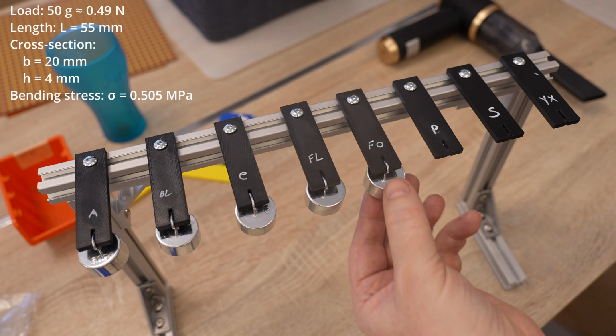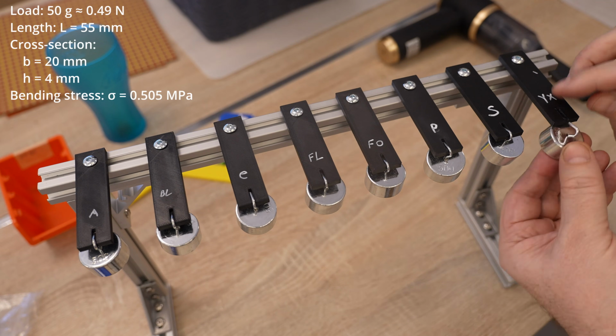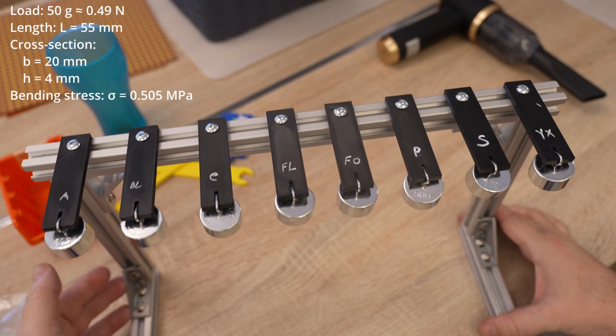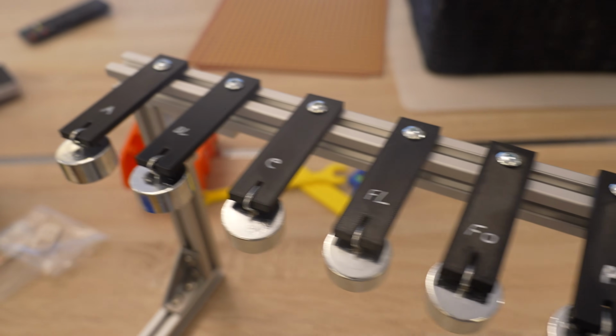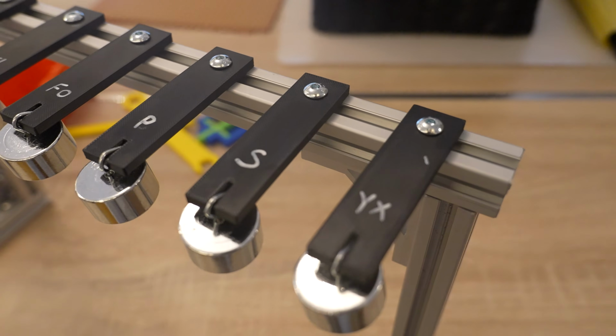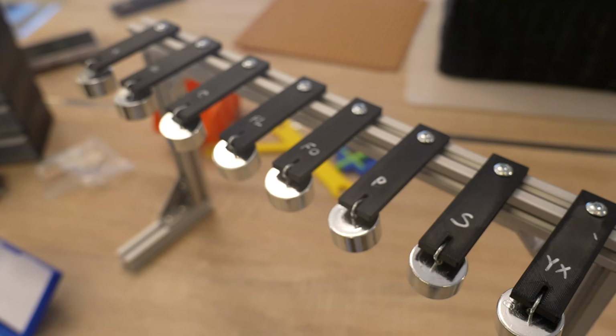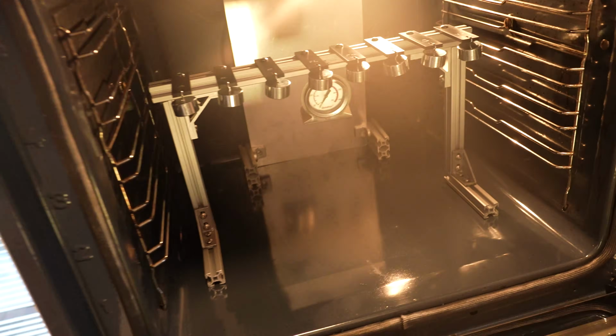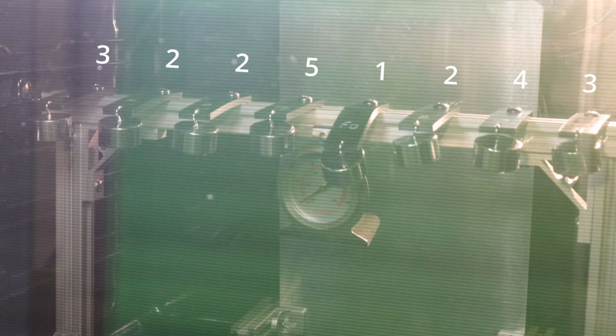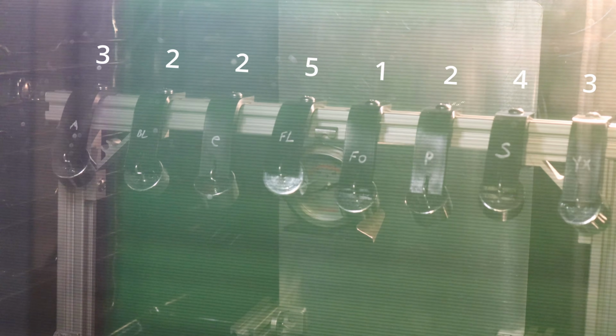The length of the aluminum extrusion is 55 millimeters, and the cross section is 20 by 4 millimeters. And with this the bending stress is approximately 0.5 megapascals. In ISO 75 they are using 0.45, which is quite close. And because of the bigger load, several objects started to deform at the same time, and you can see the order on the screen now.